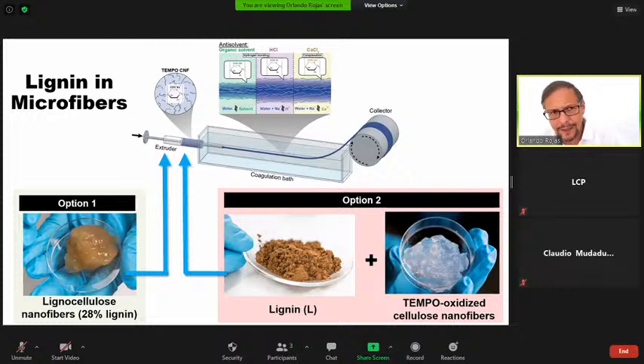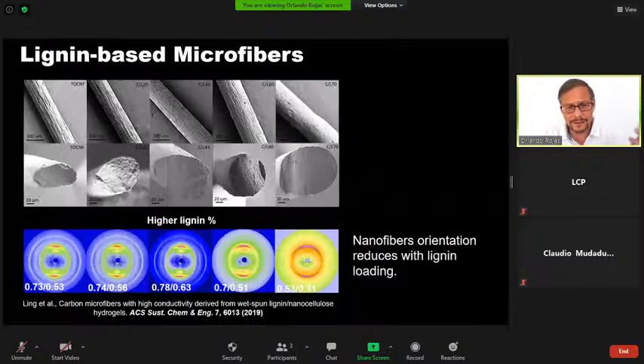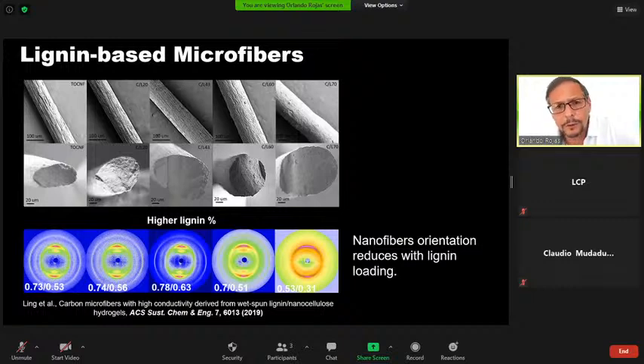And that combination, the same that I presented for membranes, is actually a quite interesting one, because combining the two, then we can produce a material that is strong enough to be drawn in the spinning bath and to produce a filament. And what is beautiful about these filaments is that those filaments have some degree of order and alignment. Therefore, they are relatively strong. Of course, when you add lignin, the strength will be reduced to some extent. But nevertheless, there is a compromise between the addition of lignin and the nanocellulose. So we have added up to 70% lignin in these filaments, and still you can produce good filaments like the ones on the far right. And that vertical column, these are 70% lignin, 30% nanocellulose.